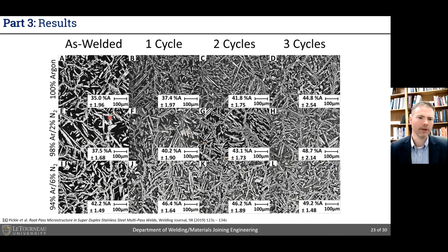And so here's the results. They performed all of those series of experiments, with these 3 different levels of shielding gas. And in case 1, 100% argon, you can see that we do have lower amount of austenite in the root, while as we increase our nitrogen shielding, we do increase our starting austenite content. Now, as we apply the same thermal cycle, you can see in all cases, we begin to grow the secondary austenite, which continuously increases with these application of the 3 thermal cycles that were directly measured from the weld.